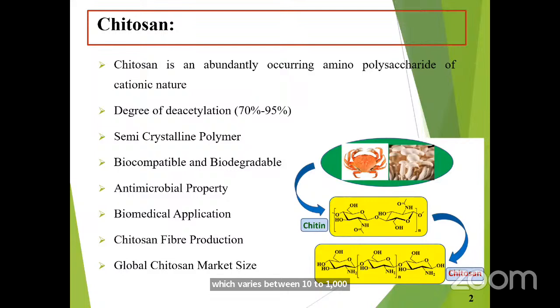Furthermore, it is also a non-toxic, biodegradable and biocompatible polymer. Various studies have shown that chitosan possesses antimicrobial effect against bacteria, fungi, and viruses. The cationic amino groups carried by the C2 position of glucosamine units of chitosan are responsible for the formation of polyelectrolyte complexes with anionic groups and different polyanions like carboxylic acids, alginate, xanthan, carrageenan, carboxymethyl cellulose, pectin, and polylactic acid.